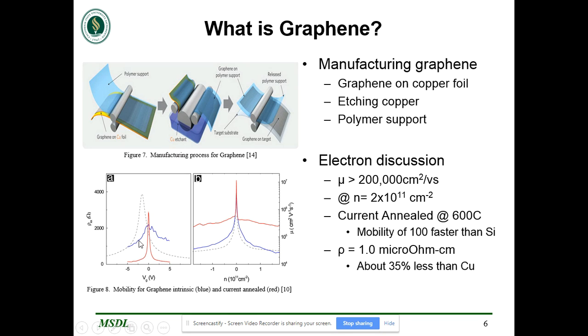Over here, you see this diagram right here. The blue line is just intrinsic graphene. The red line is where they've annealed it. They did a current annealing at 600 degrees Celsius, and this is where you get some better peaks. Then the red here is the current anneal. Look how high that gets for mobility. Unbelievable mobilities. And hey, since there's high mobility, you lose the resistance: 35% less resistance than copper, 1 microohm per centimeter.